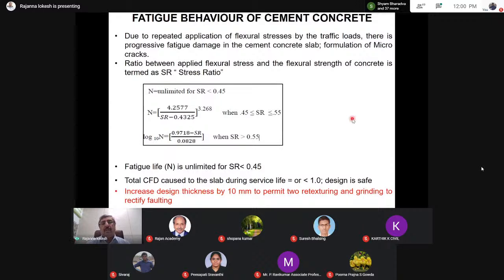Fatigue behavior of concrete pavement. Due to the repeated application of flexural stress by traffic movement, fatigue damage is caused on the concrete surface, which can be in the form of micro cracks. The ratio between the applied flexural stress and the flexural strength of concrete is called the stress ratio. It is always felt that if the ratio between applied stress and flexural strength is less than 0.45, it will have a long fatigue life.